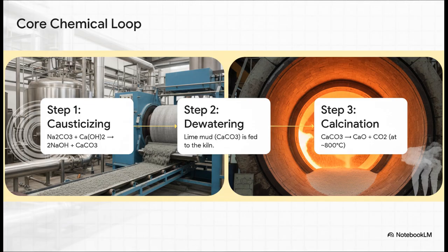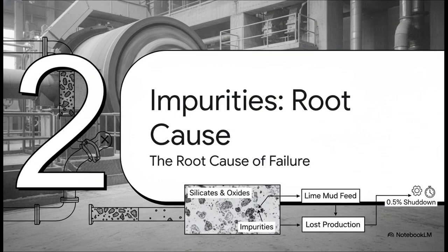And inside, once it hits about 800 degrees Celsius, that's when the magic happens: calcination. The CaCO3 breaks down into the CaO we need, our good lime, and releases CO2. The entire reason this multi-million-dollar piece of equipment exists is to make this one reaction happen and close the chemical loop.